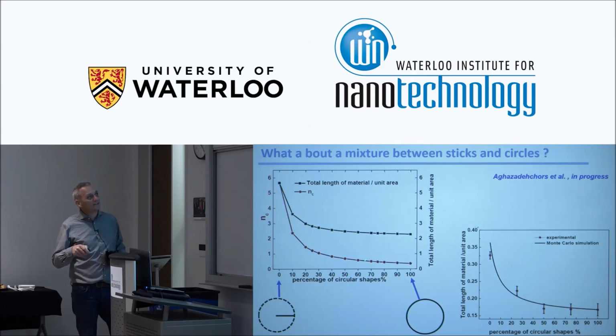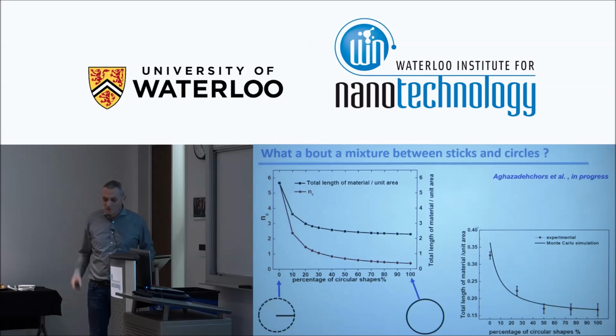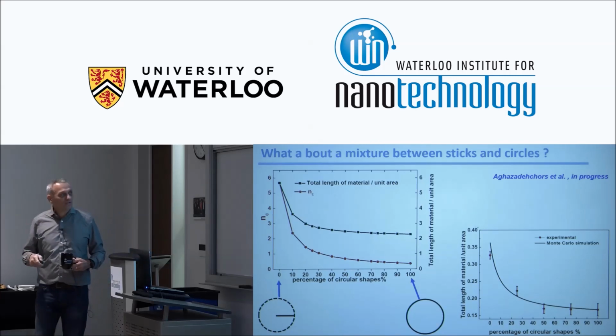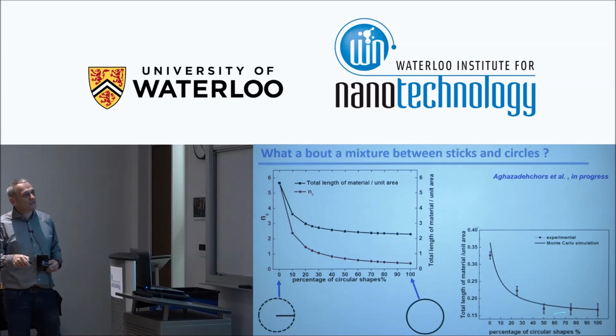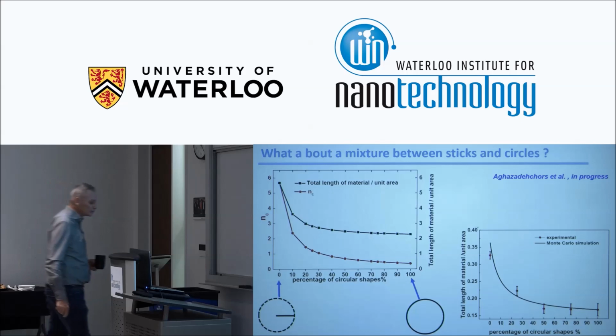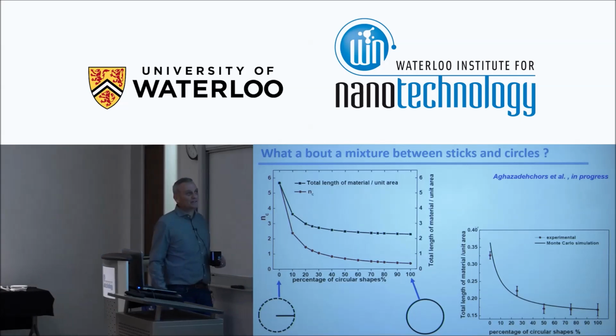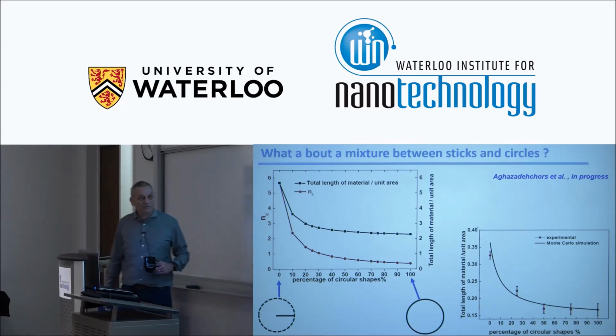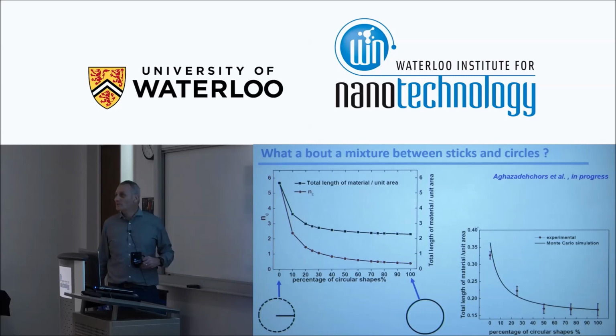We can play with that, and we have also performed some macroscopic experiments with long sticks and long circles, and the experimental points are in rather good agreement with the simulation. We are happy with that because when you are making a simulation, even if you try to be very careful and honest, you can from time to time make some mistakes, and it's nice to retrieve the same result with an experimental approach as well.